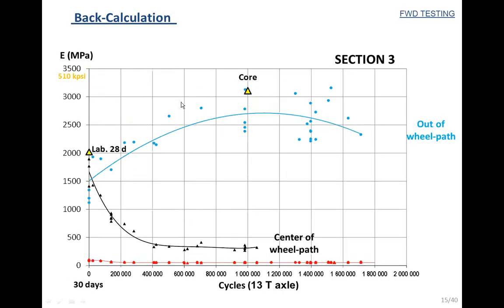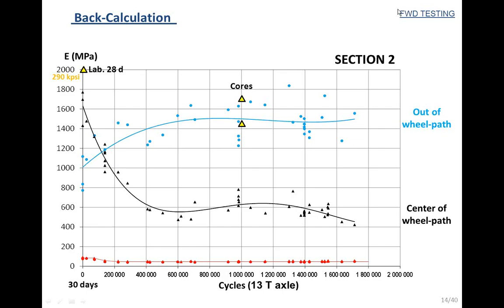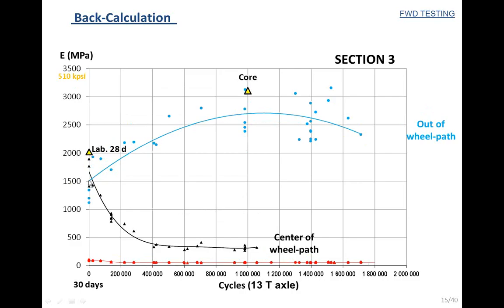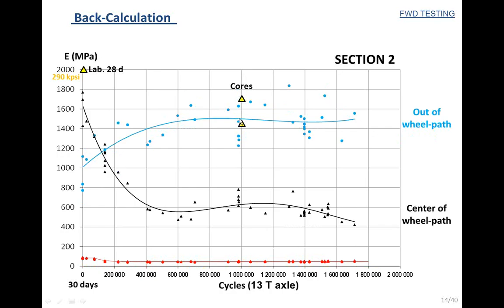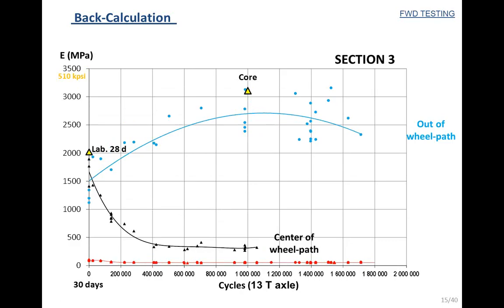Yeah, for section number 2 that you are watching right now, there was a compaction problem for this line. So that is the reason why this modulus is very high. The realistic values would be for section number 3. For section number 3, the original modulus for the non-loaded line was similar to the loaded line, and this increased a lot. In fact, when we took a core from section number 3, the modulus was around 3000 megapascal. And when we took the core from section number 2, the modulus was around 1600 megapascal. So we have the feeling that the results we are obtaining from back calculation are realistic.